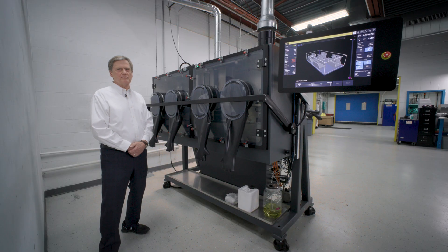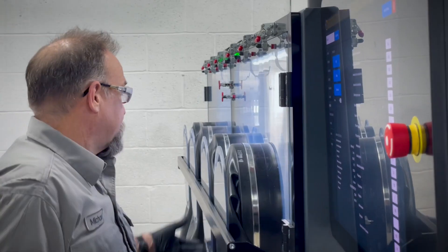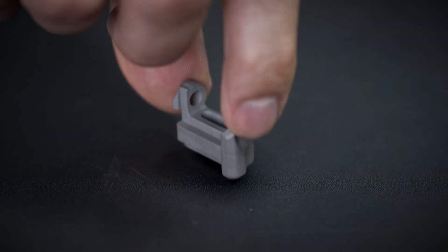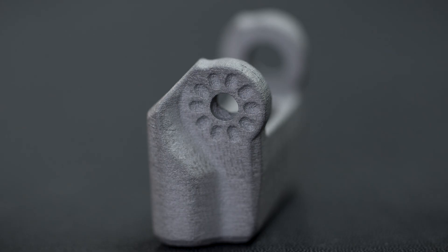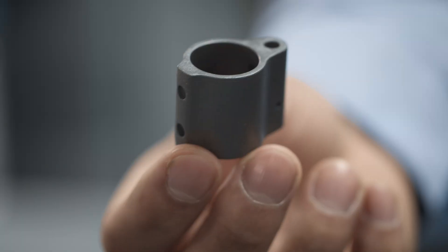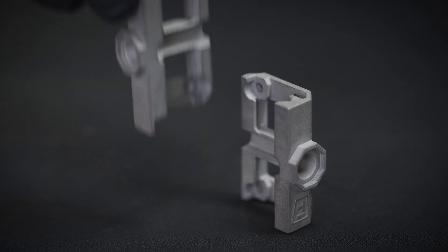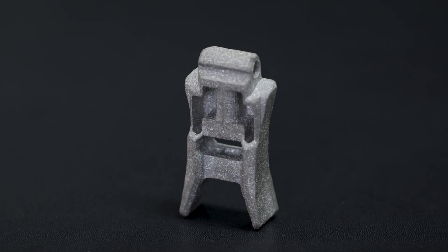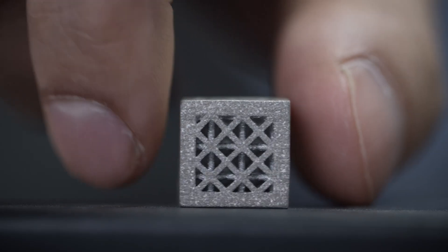What we have ended up with here in Detroit is the first production scale titanium binder jet printer. The P1 production unit is very good at achieving fine details of complex parts. The P1 has allowed us to achieve some of the best surface finish we've ever seen on an additive manufactured part — we're achieving in the three micron RA or lower range on almost all features.